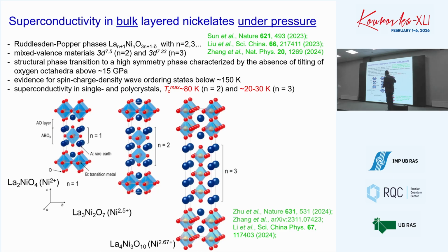And very recently, like 2 years ago, people managed to find superconductivity in double layer and three layer nickelates, which are entirely mixed valent: 2.5 plus, 2.67 plus, 2 and 2/3. Although the single layer nickelate has been known for decades, it is some kind of Mott insulator with a large energy gap, and you need to either dope this system or pressurize it heavily to make it somewhat metallic. I do not actually know any results that make this system metallic.